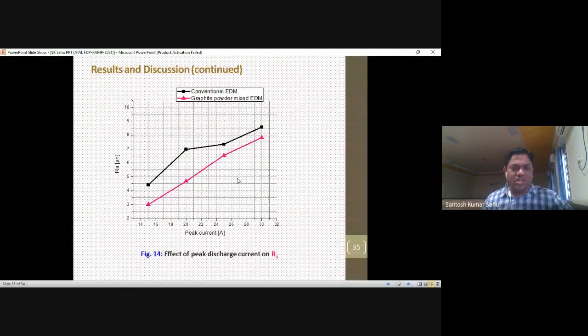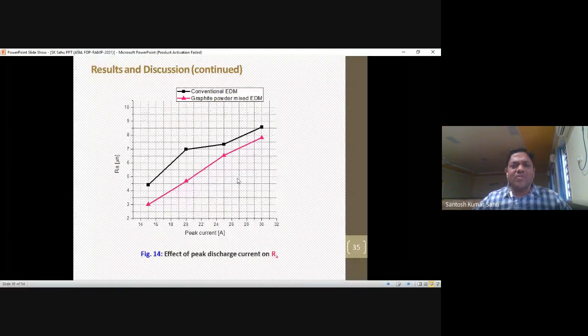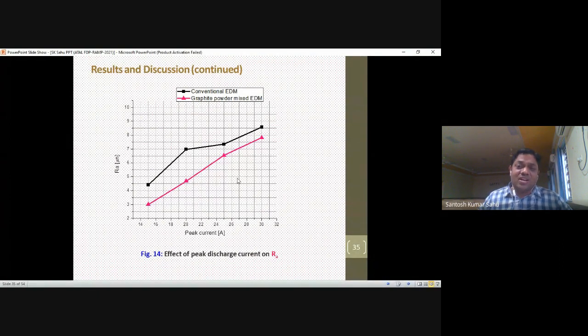Again, in figure number 14, we have to see the pink line is the graphite powder mixed EDM, and the black line is the conventional EDM. So here also you have to see the relation between the roughness value Ra with respect to the current. Again, as the intensity of the spark, the intensity of energy, increases, MRR also increases, and the Ra value also depends on your intensity of spark. If intensity is more, the Ra value will also increase.